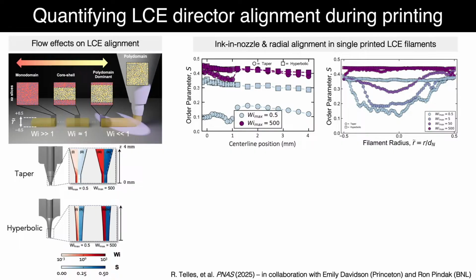So with that in mind, when we're at a Weissenberg number less than 1, you can see that we have very low order. When we go up to a Weissenberg number of basically 500, we get a very large amount of order where the order parameter is approaching 0.5. And then you can also see that in a tapered nozzle, there is a big difference in terms of the center line position values. And in the hyperbolic nozzle, it's essentially uniform across the entire height of the nozzle. So this extensional flow helps to enhance the degree of order.